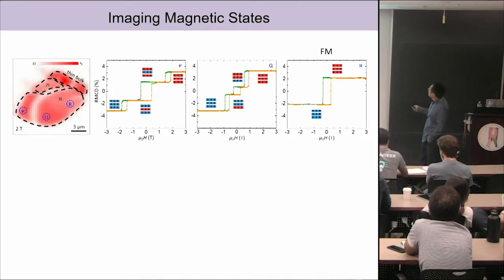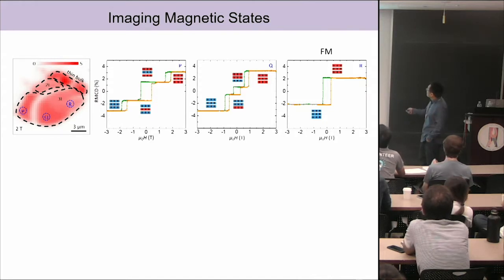For the ferromagnetic states, at this particular spot R, we do see a ferromagnetic state show up. But in P and Q, they have 3 spin flip transitions.